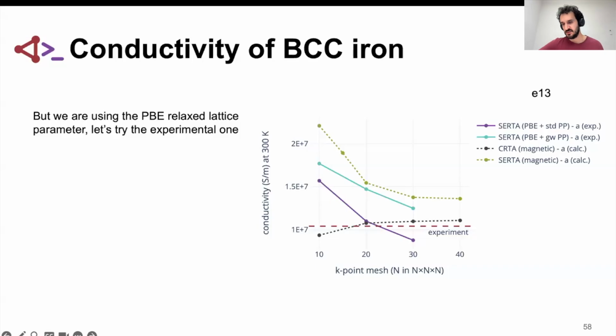But in this example, we were using the relaxed lattice parameter from PBE. Let's try using the experimental one. This green line is the relaxed PBE lattice parameter. And now when we use the experimental one, we obtain this teal line and this purple line.